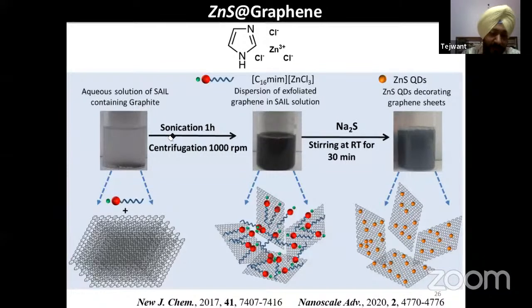The first step was extraction of graphene, where the ionic liquid decorates the graphene surface. Once we added the sodium sulfide and stirred the solution at room temperature for 30 minutes, we have found the decoration of exfoliated graphene sheets with zinc sulfide quantum dots. In the first step, again I am repeating, we generally exfoliate the graphene nanosheets which are being decorated by the template or surface active ionic liquid present over there. So from the ionic liquid we were having these Zn2+, and we have added from outside sodium sulfide, stirred the solution at room temperature for 30 minutes to have finally graphene decorated with zinc sulfide quantum dots.